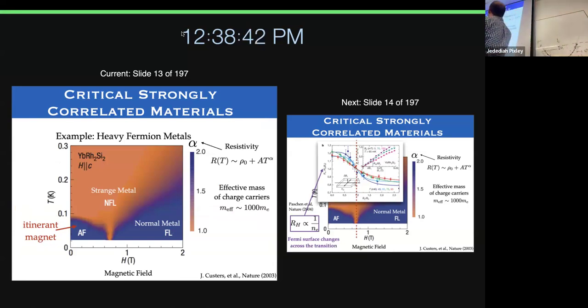So this is an example of a heavy fermion metal. It gets this name just because the effective mass of the charge carriers is about 1,000 times the mass of an electron, dressed by the magnetic interactions in the system. And here, the color is the resistivity exponent. So strongly correlated, everybody shows this picture, it's pretty famous. So blue is a metallic, T squared. So I have a metal over here, a metal over here. This is actually an antiferromagnet, so it's broken time reversal symmetry. And then you go through this transition by applying magnetic field, and you have this linear in temperature resistivity that defies a simple explanation in terms of a metal.